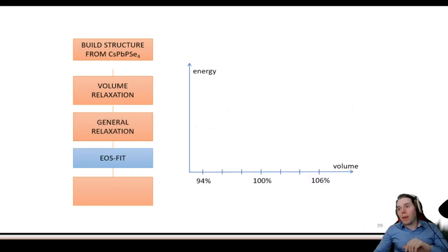And then finally, we manually, again, compress and expand this material a little bit, both to examine how soft it is and to make sure that we really have the right crystal structure. So I say how soft it is. Why? Because if you start with this material at its original volume and you push on it and the volume becomes smaller, the energy will go up. And if it goes up a lot, it means that the atoms are repelling each other very much, that it's resisting the pressure you're putting on it, and that it's actually not very soft. And the same, of course, if you're trying to pull the material apart. So from this, you can estimate the hardness without bumping your toe, let's say.